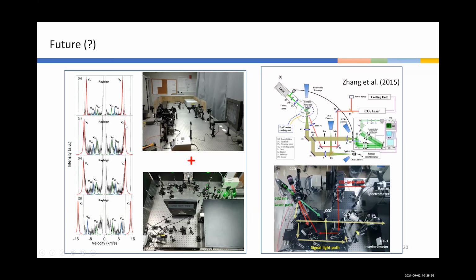Look at this red line here. This is an example of ice. You can see the VP of the ice gradually gets closer and closer to the diamond, and then finally will overlap with the diamond. We can never see the VP anymore. So that means for mantle minerals, when we go above 25 GPa, we cannot get the information of the P wave at all. So this is very unlucky.